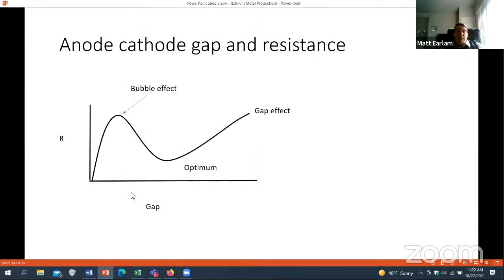So you have an effect, right? Because of the gas bubble void fraction in that annular space, you have a change in resistance. As the gap gets smaller, obviously we can short it, and so we have zero resistance. Resistance will go up as the gap goes up a little bit, and there's more volume. The volume of the bubbles increases inside compared to the volume inside the gap, and so you get to a point where the resistance starts to go up, and then it starts to come back down as the void fraction of the bubbles gets smaller in terms of the space inside the annular space. And then eventually it'll start to go up again because you're way far away from the cathode.